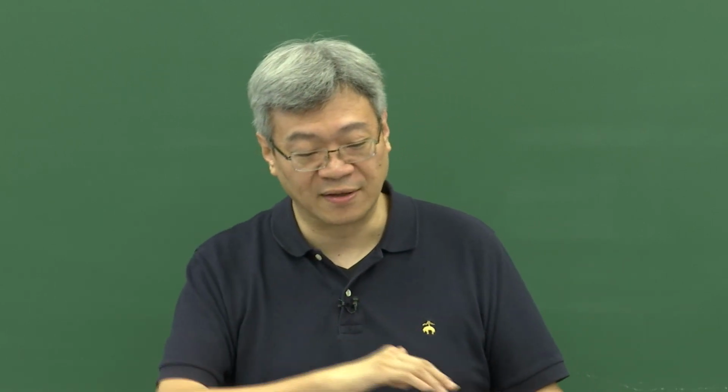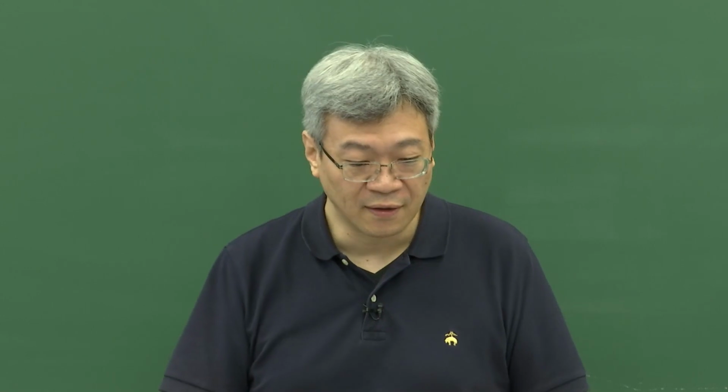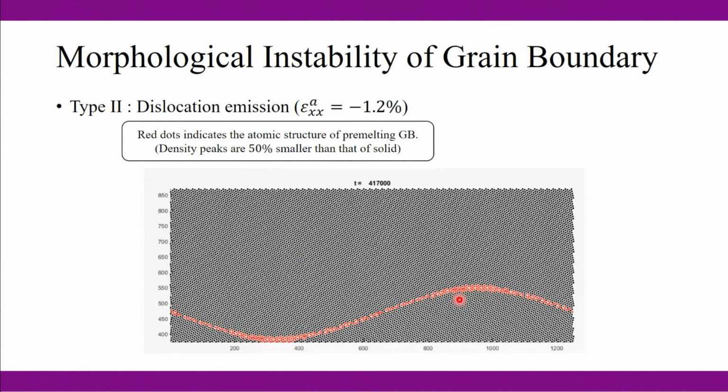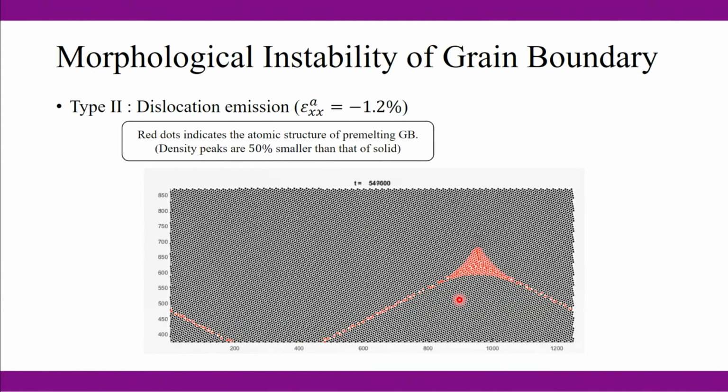So that's why, being sandwiched by nearby solid, you are expecting this kind of instability. Okay, just to connect it to real case scenarios, this is known to happen in geological systems. You have minerals and they have grain boundaries. Sometimes the solution, the water, gets into the grain boundary region, penetrates into the boundary region and makes it softer. So stressed minerals inside the core generally have cracks from the grain boundary. People try to study that, and it is similar to what we are seeing here, just at a different scale.